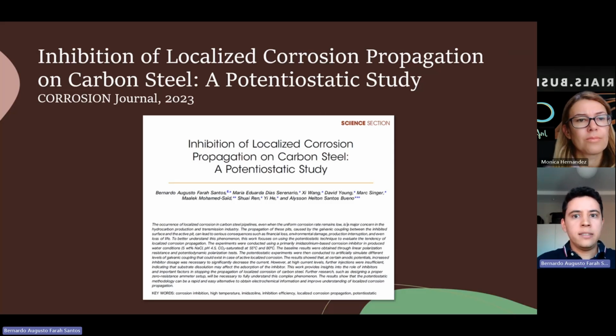Just to recap, with the potentiostatic technique you can apply a potential to your working electrode, and in consequence there will be a current flowing. And that current could be interpreted as the current flowing in this local galvanic coupling that happens on the pipeline. So our main idea was applying different potentials to simulate different environments in which localized corrosion could propagate. You could have a surface around the pit covered with iron carbonate that would lead to one difference in potential between the pit and the surrounding areas. You could have the surrounding areas covered with corrosion inhibitors that would lead to another difference in potential.